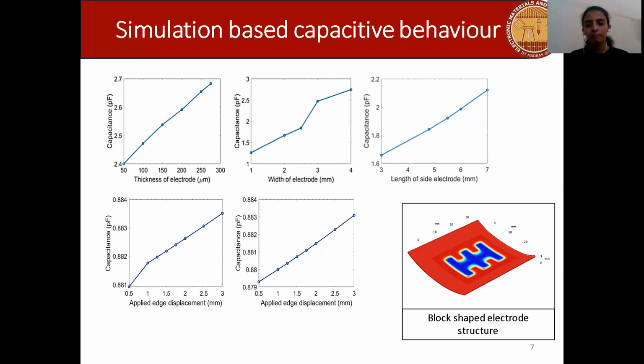So overall, if we compare the values of a square spiral, block-shaped and comb-like structure, the comb-like structure was observed to show higher capacitance values, that is a better sensitivity compared to these two structures in both plane and bent conditions.